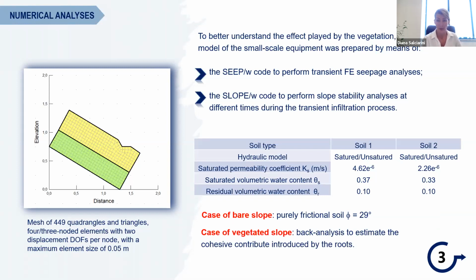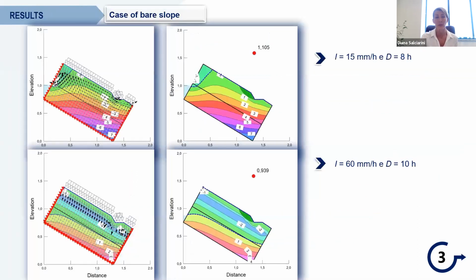As for the hydraulic parameters of the model, we used the results of the previous experimental tests performed. For the case of the bare slope, we used a purely frictional soil with a friction angle equal to 29 degrees. For the case of the vegetated slope, we performed a back analysis to estimate the cohesive contribution introduced by the roots, neglecting the additional beneficial effects of the hydrological type. As for the rainfall patterns adopted, we used the potential seepage face boundary condition available in the SEEP code.